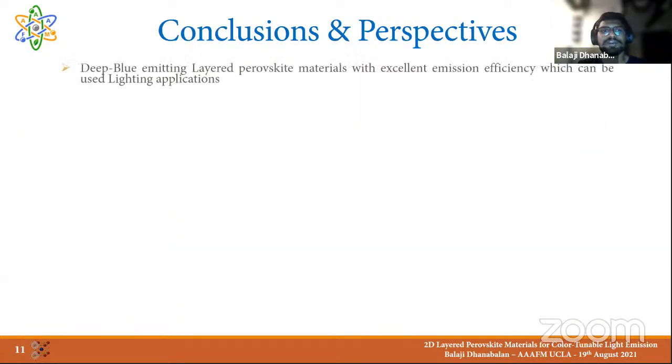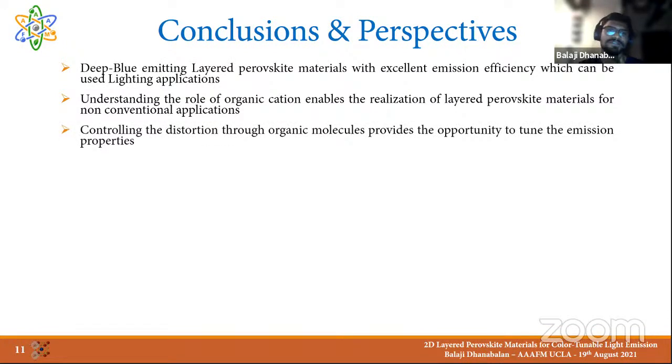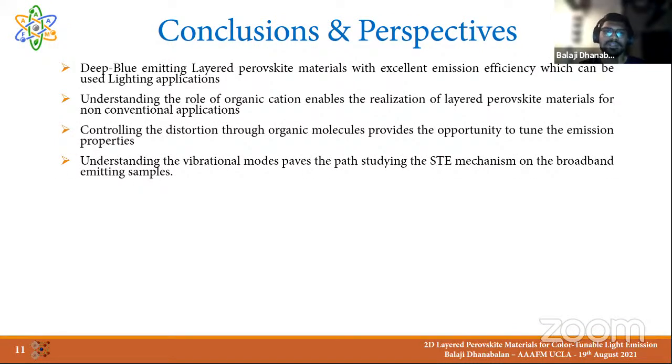So with that, I would like to conclude. We were able to produce a layered perovskite material with a simple synthesis technique, which showed deep blue emission. By playing with the organic cations, we were also able to tune these optical properties from deep blue to white light emission, to warm white light and to pure white light emission. That was due to the distortion created by these organic molecules. We also studied these materials with Raman spectroscopy to study the vibrational modes, which paves the path to study the STE mechanism.